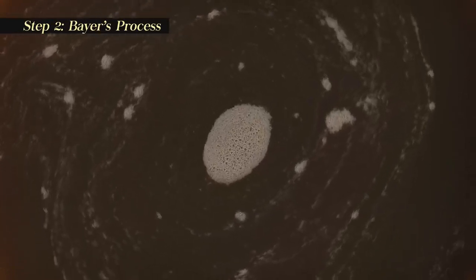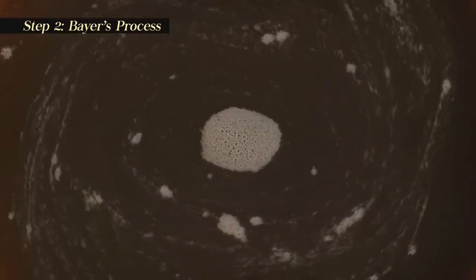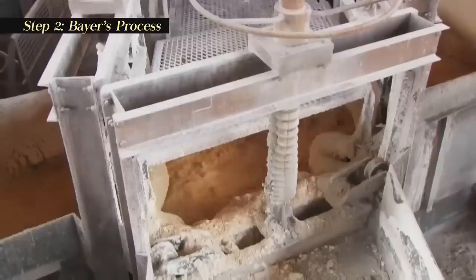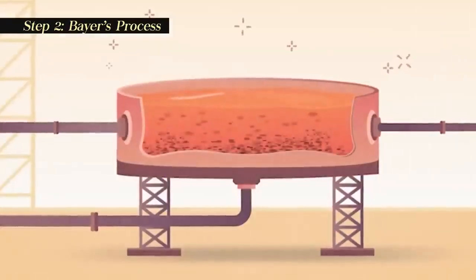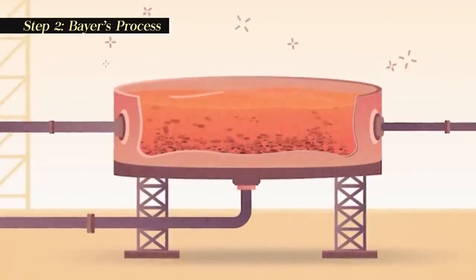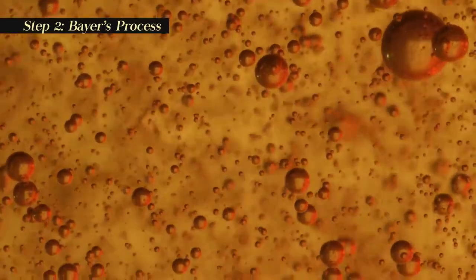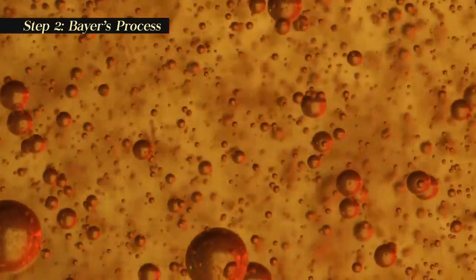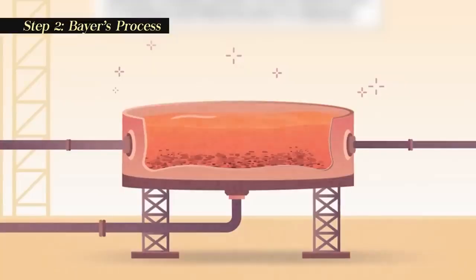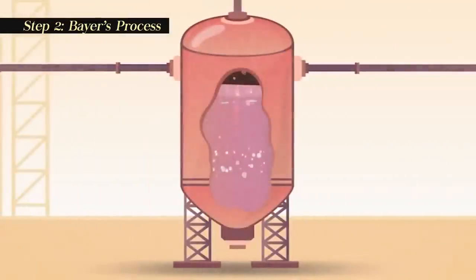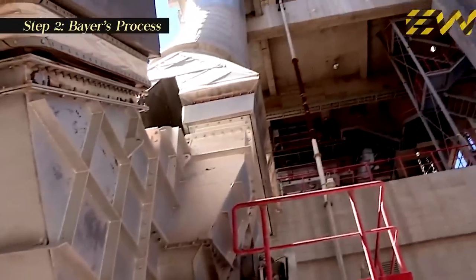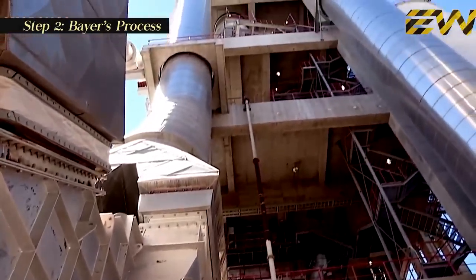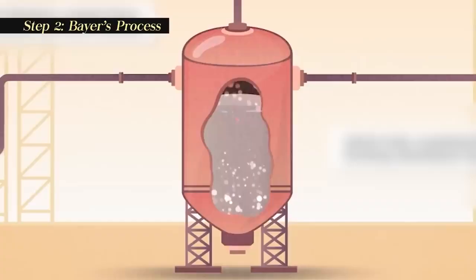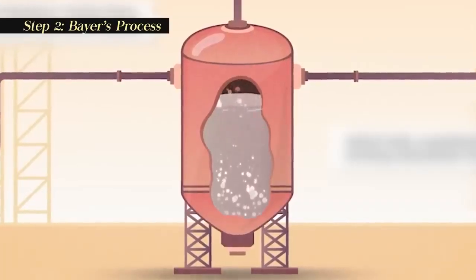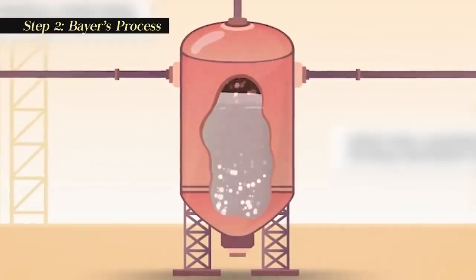After the impurities have settled out, the remaining liquid, which looks somewhat like coffee, is pumped through a series of cloth filters. Any fine particles of impurities that remain in the solution are trapped by the filters. This material is washed to recover alumina and caustic soda that can be reused. The filtered liquid is pumped through a series of 6-story tall precipitation tanks. Seed crystals of alumina hydrate, alumina bonded to water molecules, are added through the top of each tank. The seed crystals grow as they settle through the liquid, and dissolved alumina attaches to them. The crystals precipitate and are removed.